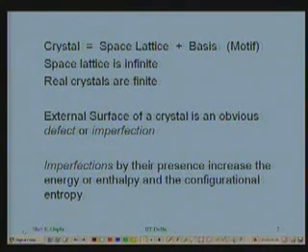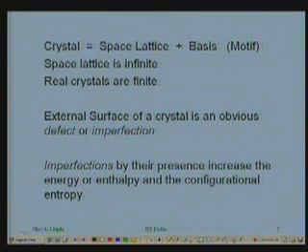We shall see that. Therefore, the external surfaces of a crystal become the obvious imperfections. The external surface of a crystal becomes an obvious defect, an obvious imperfection. In other words, what I have described about this external surface could have been a flat surface, not a cylindrical surface. These imperfections, by their presence, like the external surface, increase the energy of the system, the energy of the crystal, in other words, the enthalpy of the crystal.